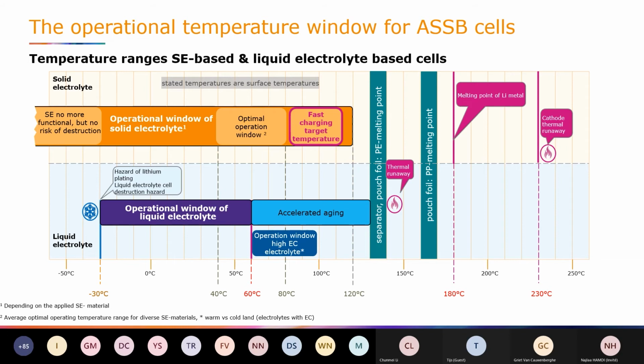For solid-state cells, the operational window is much larger, starting also at around -30 degrees, but going up to 120 degrees Celsius. The window for optimal operation is relatively large and leads also to additional engineering measures if you want to integrate the solid-state cell into an automotive application. For the fast charging process, you should reach even higher temperatures, up to 100 degrees Celsius and more. In terms of safety, you are more or less safe because the thermal event occurs at much higher temperatures and thermal runaway starts at more than 230 degrees Celsius.